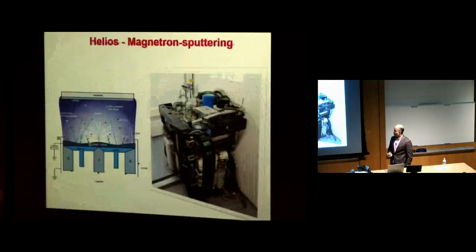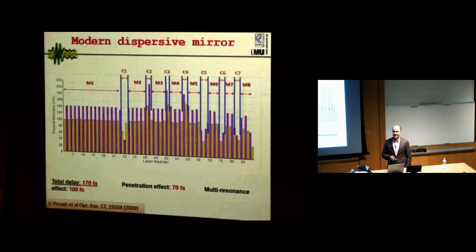Another very important point is how to produce the structure, because I think we have a question, right? C1, C2, and yes, that's what I told, that this whole structure is divided: M is mirror, and C is cavity. It means this particular structure consists of seven cavities and eight mirrors. When we make a design by changing the thicknesses for this cavity, we change the reflectance for these mirrors, and we change the thickness for this cavity. The thickness of this cavity should be very precise, otherwise this cavity will not work with our certain frequency. It means we need to control each layer thickness very precisely.